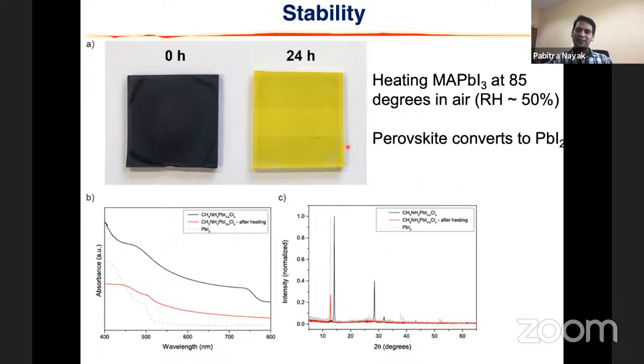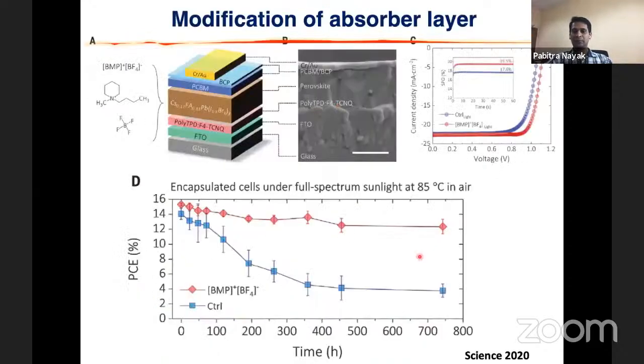Why? Because these first generation things are very, very fragile. They don't like a little bit of moisture. So the black form, which generally absorbs a lot of light, goes to yellow form, which is not a very good light absorber, and the efficiency really goes down. So we at TIFR are trying to make these things very stable, trying to understand how you can make this stable so that it lives long and gives power for a longer amount of time. In that regard, we have a paper that came up in Science in the year 2020.